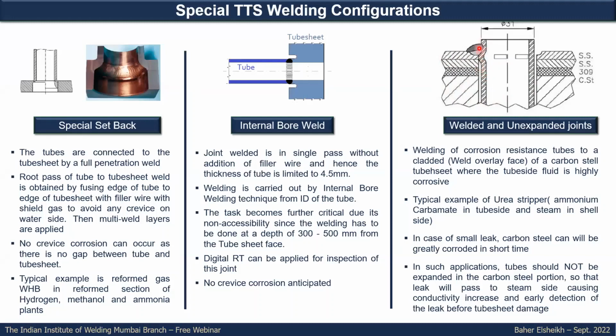And in this one, the welding between the tube and the tube sheet face, the cladded surface, it is highly recommended to avoid doing the expansion. And if you can remember from what we said in our earlier slides, it is highly advised to do the expansion to close the crevice. But in this case, it is the opposite recommendation.